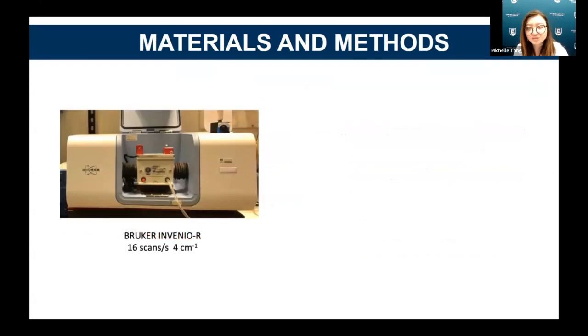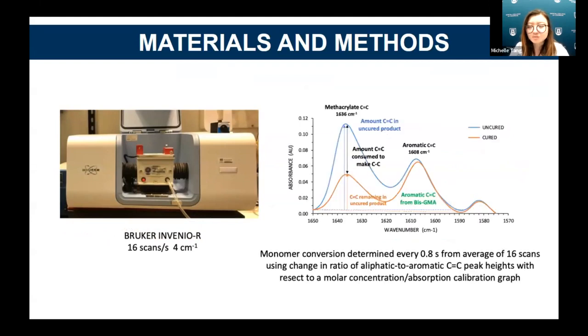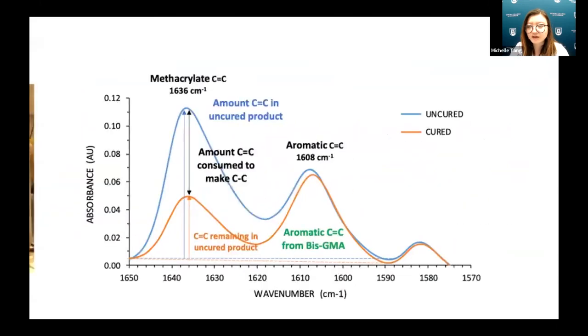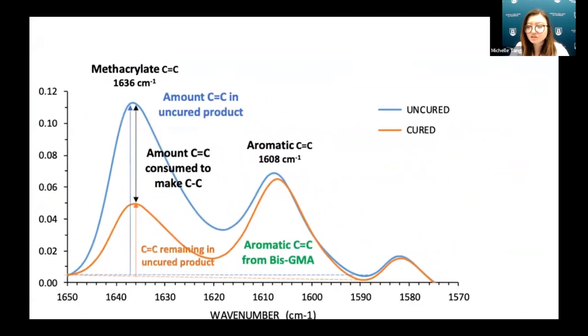Bruker's FTIR machine was used to gather data on the bottom of the flowable composite, furthest away from the light source. Monomer conversion was determined from the average of 16 scans by analyzing the change in the molar concentration of aliphatic carbons as a ratio of aromatic carbons. The change in these ratios over time determined the percentage cure. As the curing process continues, the ratio should decrease, as uncured composite resin would typically display a higher concentration of